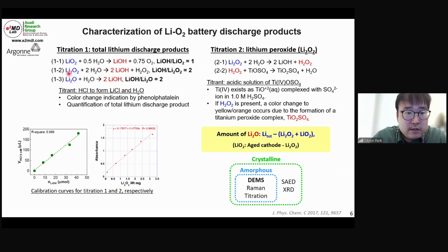From these reactions, the lithium peroxide only can form hydrogen peroxide. This is the same reaction. Once the hydrogen peroxide is formed, we can add a titrant, which is called titanium oxosulfate solution. Once they react, there's going to be a titanium peroxide complex, which has a yellow or orange color. The concentration of color depends on how much lithium peroxide formed, and is also directly related to the discharge capacity. By quantifying the lithium peroxide and the total lithium discharge product, we can use this equation to obtain a more accurate result.